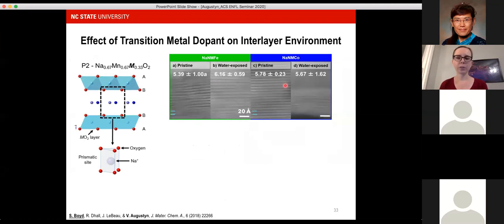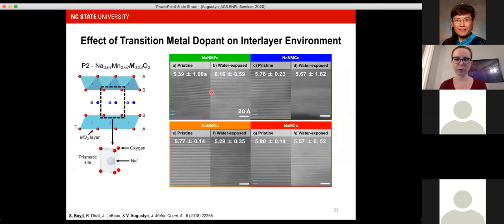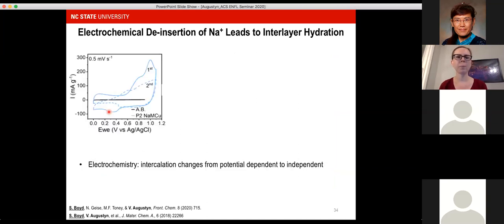So we looked at some other compositions. We did scanning transmission electron microscopy of the materials. Even some of them became very reactive just due to the exposure to water, which is pretty well known. And so it was kind of driving the point that the transition metal content was dictating what the interlayer environment would be. We did some operando X-ray diffraction. This is now the in situ cyclic voltammogram showing, again, we have this first cycle where there are clear peaks in the cyclic voltammogram, but they disappear on subsequent cycles.